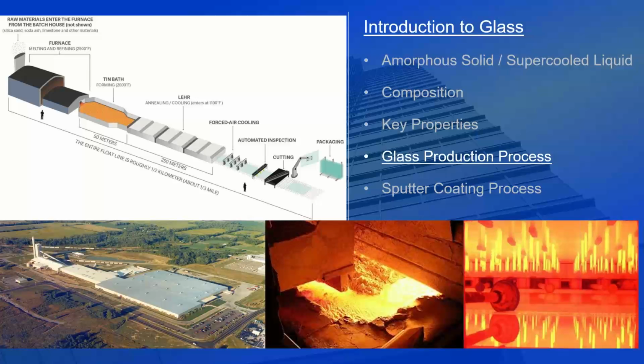The ingredients are melted in the furnace at a temperature of around 1,600 degrees Celsius, 2,900 Fahrenheit. Again, they're allowed to cascade gently onto the top of the molten tin at about 1,100 degrees Celsius. At the far end of the tin bath, closer to the annealing leer, that temperature drops down to about 600 degrees Celsius. The image on the bottom right corner shows a view inside of the tin bath, and you're looking at guide wheels, which help to guide that ribbon of glass through the tin bath, while also helping to control the speed of the ribbon through the bath.